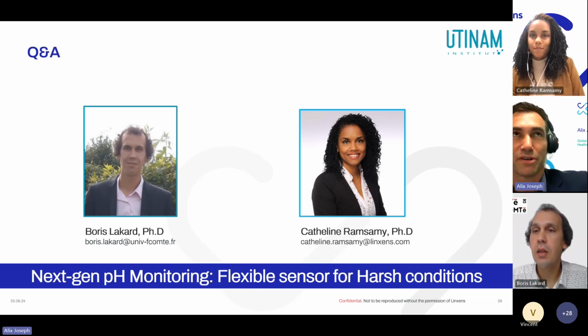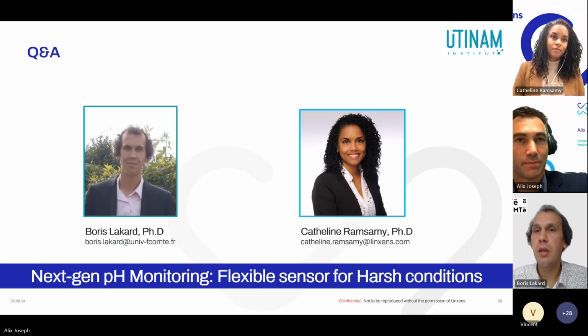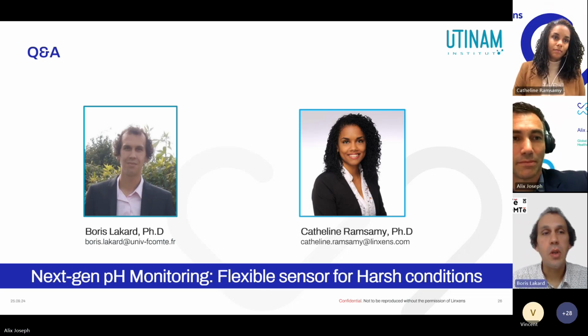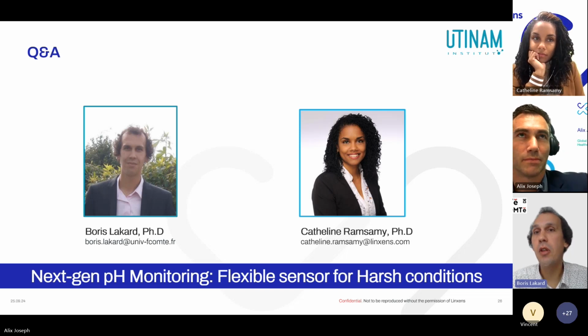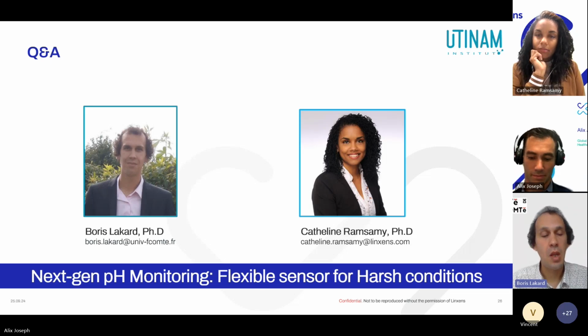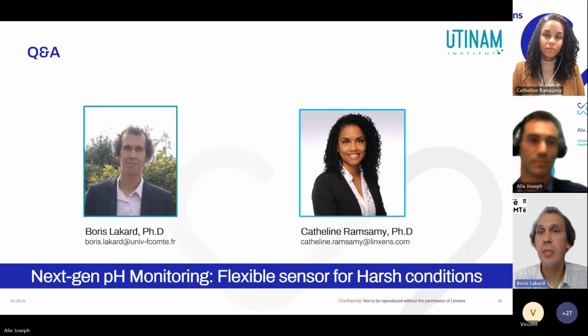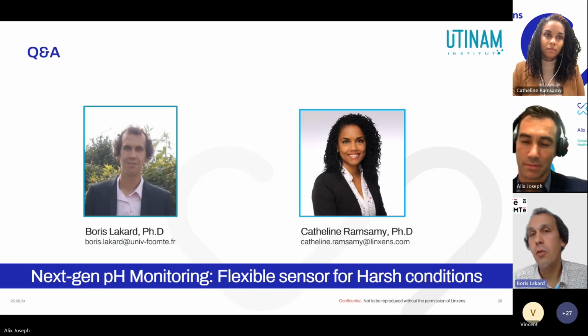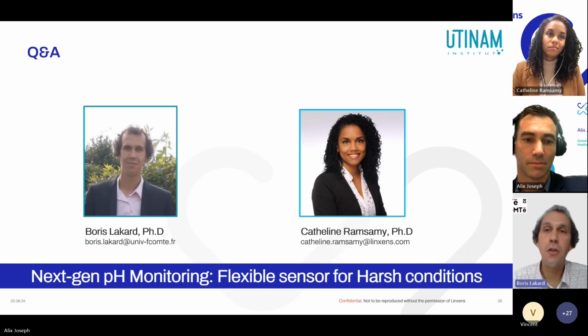And is the sensor response reversible? Yes, we have observed that the reversibility was very good in aqueous solutions. We have no problem. We have no drift. And in hypochlorite solution, it's a little bit more complicated, but we have a correct reversibility, maybe not as perfect as for the aqueous solution. It's a little bit more complicated in a hypochlorite solution, but you have a good reversibility too.